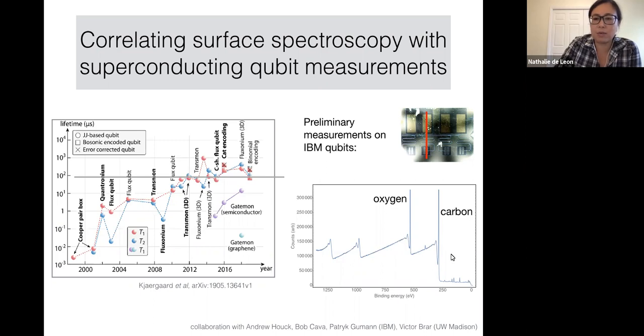I thought we were going to see some different surface states and particular contaminants that we could get rid of, but actually all that we saw was carbon and oxygen. We couldn't even see through to the silicon or aluminum, which means that these things are covered with such a thick layer of adventitious carbon or fabrication residue that we didn't even have access to the surface. So this had to be at least 10 nanometers thick. And just to give you a sense of the kinds of losses we're talking about, if you had a surface participation ratio of something like a part per million, then just a few nanometer layer of PMMA is lossy enough to account for the kinds of limiting Qs that people see in these resonators.